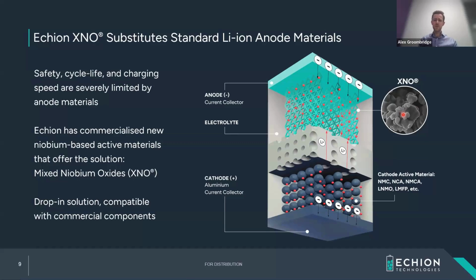You can't fast charge graphite because of lithium dendrite formation. You can't take it to low temperatures as well. LTO can indeed do this, but has limitations on energy density. And silicon, while it can fast charge and it can operate well, it doesn't last long enough for these kinds of applications. That's where we focused. We've got a drop-in solution here, so we just use normal liquid lithium ion, normal battery manufacturing, and combine it with normal cathode materials along the way. So I'll take you through the fundamentals of roughly how the material works, and then we can go into a bit of cell performance and then back along to the link back to mining.